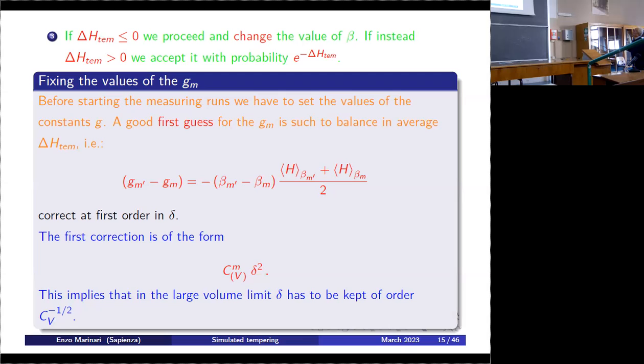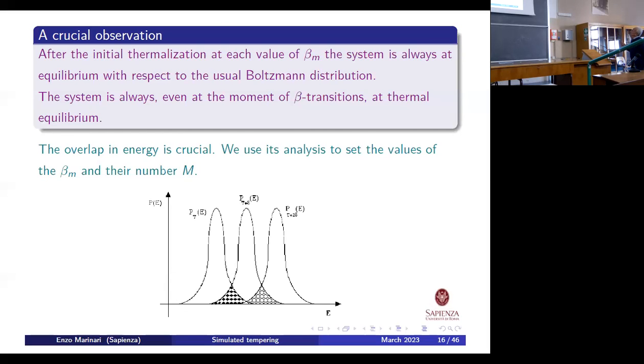So what you will do, for example, at first order, you find that G_m' minus G_m is minus (beta_m' minus beta_m) times the average value of the energy at beta_m plus the average value of the energy at beta_m', divided by 2. This is correct at first order in delta beta. At second order, for example, you add a correction of order delta squared that is proportional to the specific heat of the system. So this implies that in large volume, you have to keep delta of order C to the minus 1/2. And here we go.